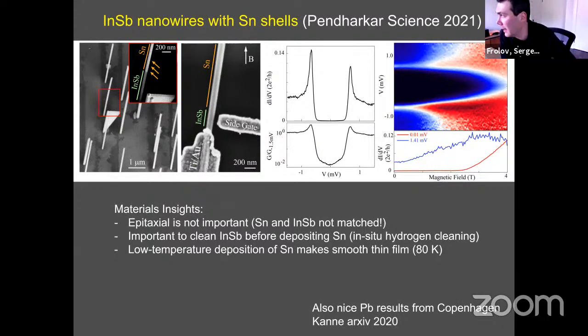I think it is all about creating extra states at the interface between the superconductor and the semiconductor. And when we work with niobium, which is what we did a lot, like in the first experiments, the way we clean the surface and niobium itself is probably prone to creating additional states in between the nanowire and the shell. And those states make the gap soft. And if they don't appear, then there's no problem. So the cleaning method we used here and the materials we used here are just not amenable to formation of these states. So we have a hard gap. That's my understanding at the moment. And I don't have very good proof of it, to be fair.